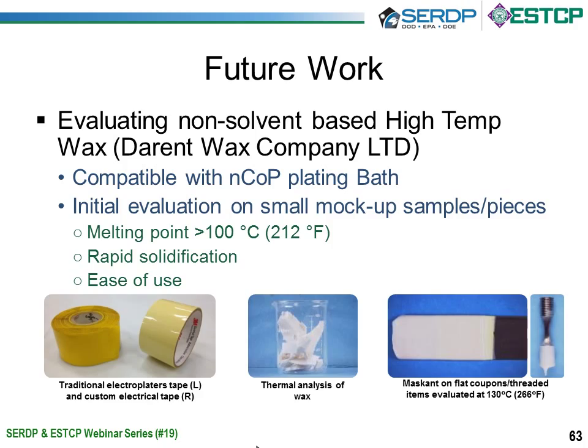And then finally, thermoplastic materials contain a great deal of solvent and require lacquer cure, which is very time consuming, which is what we used in the demonstrations that I showed earlier. What we prefer is to have a conventional wax. There are waxes available. An example of what we're showing here is a high temperature wax that we received from a company in England. And we've initiated some internal development work on utilizing that wax in the plating process.